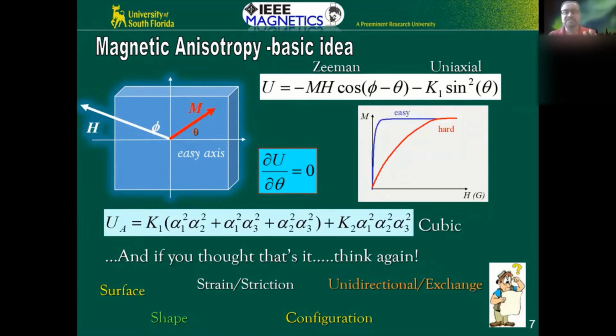Now, it turns out that exchange bias arises when you take a combination of an antiferromagnet and a ferromagnet. At the interface, depending on the difference in the anisotropy of these materials, you can actually have the spins at the interface pinned by the bottom layer, okay? And this is the so-called exchange bias. Essentially, you can think of the loop itself being shifted, depending on this amount of energy at the interface. And the coercivity can increase or decrease for a hysteresis loop. And that is because of the so-called exchange bias.